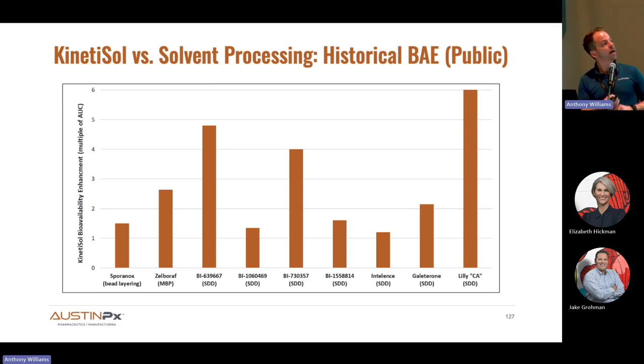from Roche. But to show that time and again, we show significant performance enhancement over spray drying, and it's rare that we're inferior. And if we are inferior, oftentimes it comes down to modifying the particle properties side, producing finer particles through modifying our milling process.